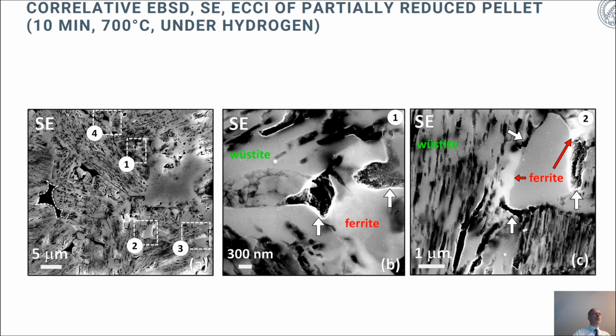Here is now a somewhat more detailed analysis of a material that was reduced under pure hydrogen at 700 degrees centigrade for about 10 minutes. What you see here, in the SE, secondary electron image, is a wide variety of different features that we want to look at in more detail. When we take this first view at this region, you see a complex interplay of the ferrite and the newly formed porosity, which is due to the mass loss. So in the areas where you have adjacent wüstite to ferrite, you very often find these pores that newly open up, like here and here.